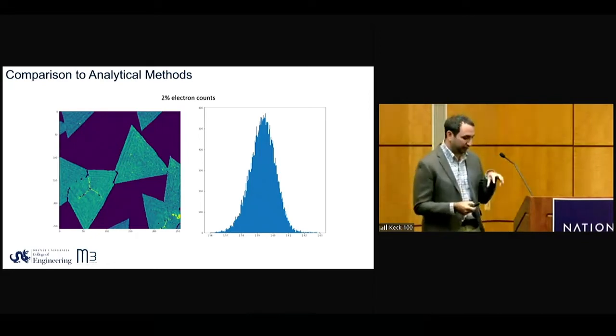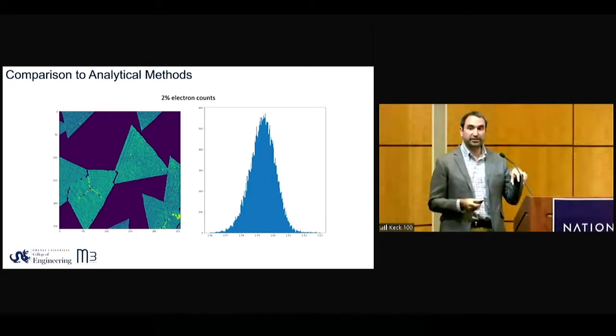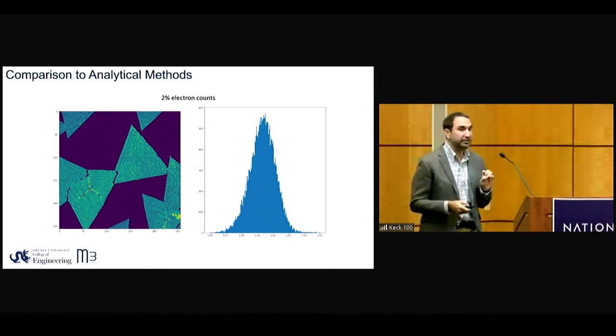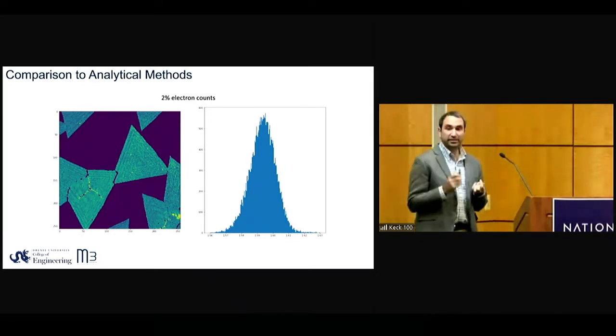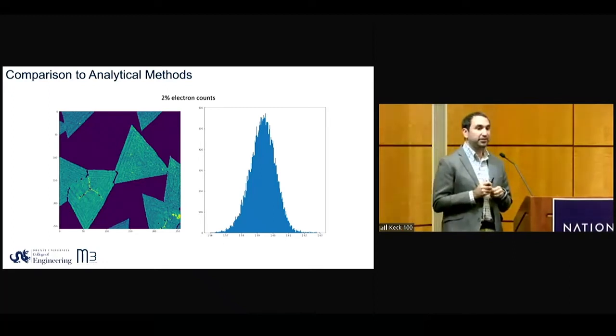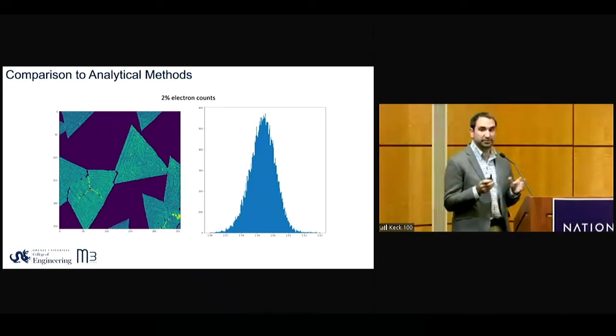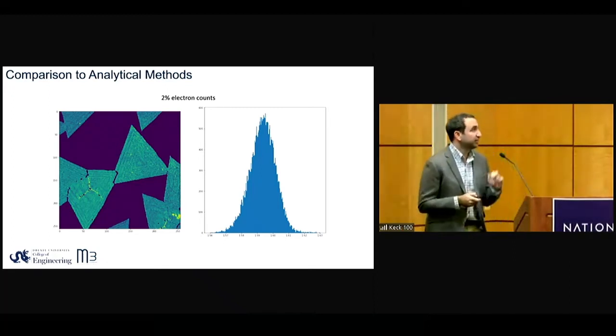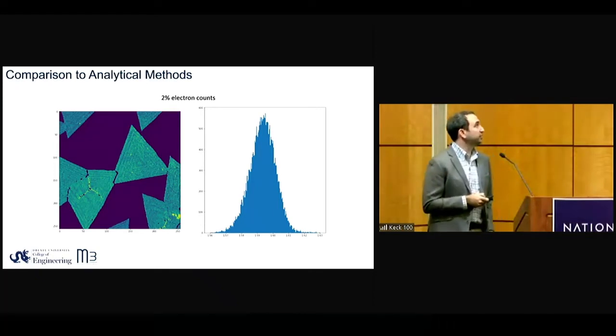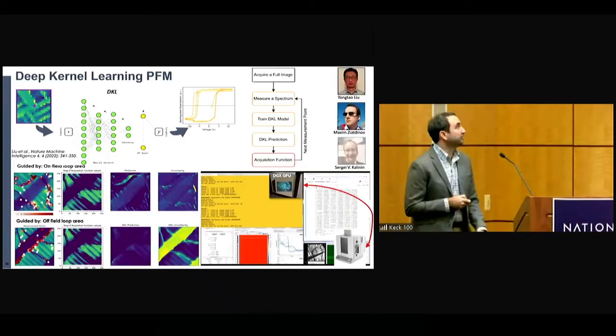Because it's a direct electron detector, we can say, okay, here's the number, and randomly apply a probability of that electron existing, and we can get down to 2% and still be able to resolve some of the key features. So this is way lower dosage, which matters for some of the sensitive materials. This is a really interesting result and a nice way of using machine learning.